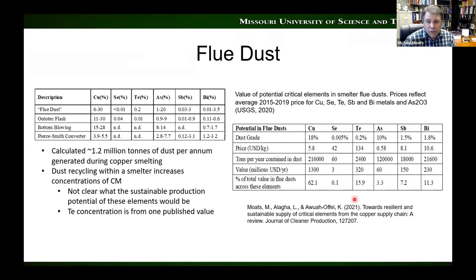Now, the selenium looks really interesting, but there's only one published value on the tellurium content in dust. So I have no idea what's really in dust, but based on the one data point, this is what it would be. You can see there's quite a bit of bismuth, quite a bit of arsenic, and of course antimony. Those are fumed off. That's one of the things that we try to do during smelting.